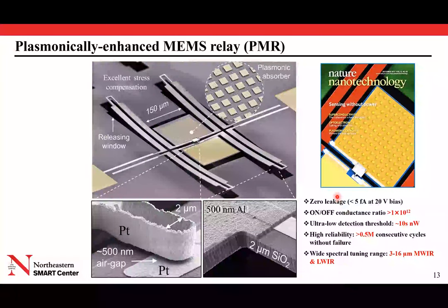First of all, we say that it is zero standby power, because basically in the open state, it's an open mechanical switch, right? So there is an extremely small leakage current. We measured less than 5 femtoamps up to 20 volts bias applied. So substantially, it's really a near zero leakage there. There is a very large on-off conductance ratio, larger than 10 to the 12. That means that this is a switch with a very steep subthreshold slope, right? It's very different from more conventional solid state devices.